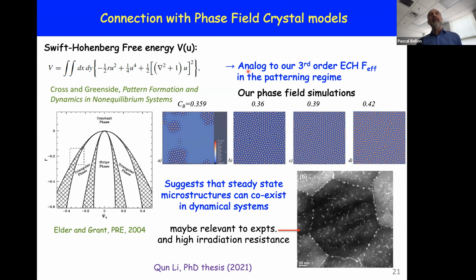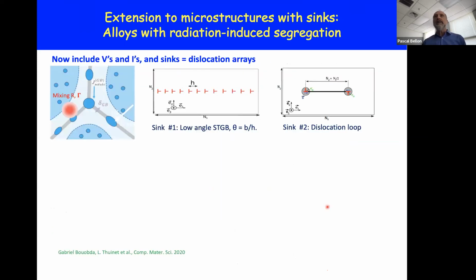In real materials, when we look at their microstructures, we know that the microstructure is complex and can include grain boundaries and so on, as I mentioned at some point in the introduction. And so we also had an interest in looking at grain boundaries. Here is an example of a case where under radiation of a copper tungsten thin film, tungsten precipitates become stable under radiation, and you see that they appear to have formed compositional patterns within the grains as well as at grain boundaries and at triple junctions. So we recently started to extend the previous model to microstructures that contain sinks, such as grain boundaries and dislocation loops, and consider what kind of coupling might exist between patterning in the bulk and patterning at grain boundaries, or whether it is possible for these two patterning reactions to coexist?